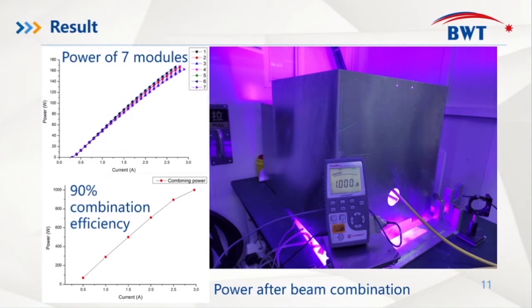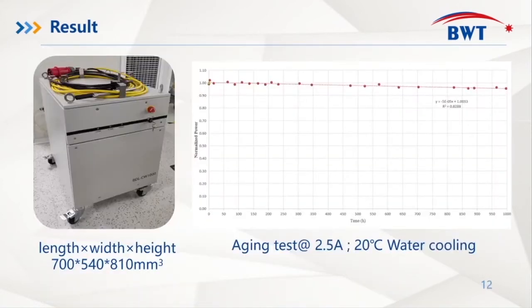We manufactured a power supply control system and QBH transmission fiber. The right figure shows the power measured after beam combination. The figure shows a photo of the blue laser system. After 1000 hours of aging under the condition of 2.5 ampere current and 20 degrees water cooling, the power attenuation of the unit is less than 3%.